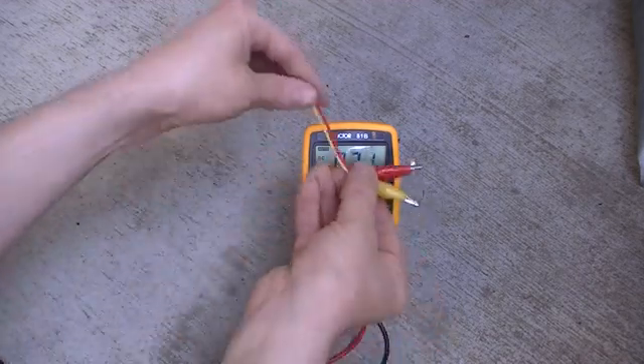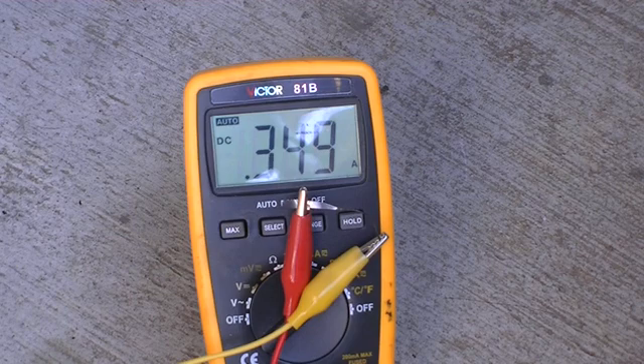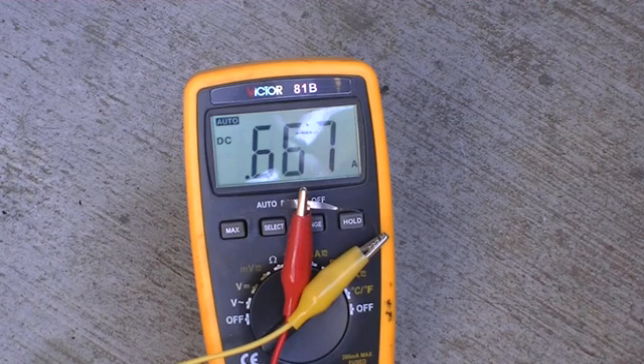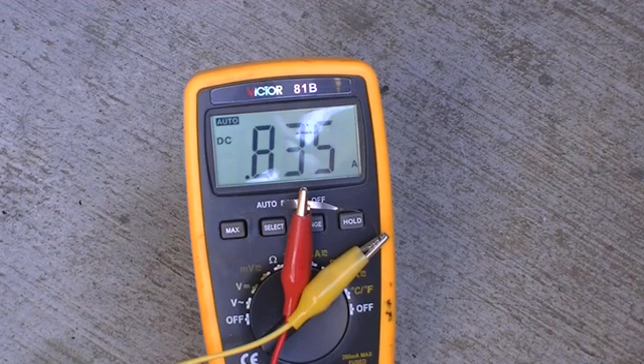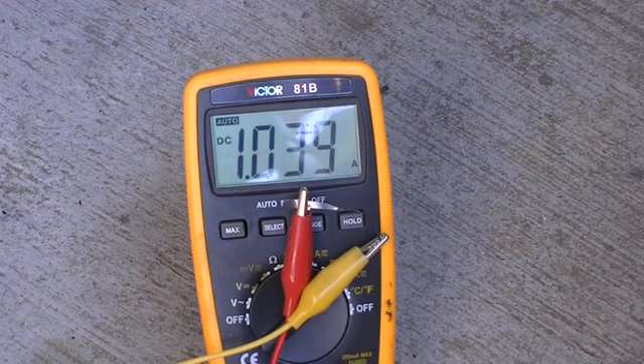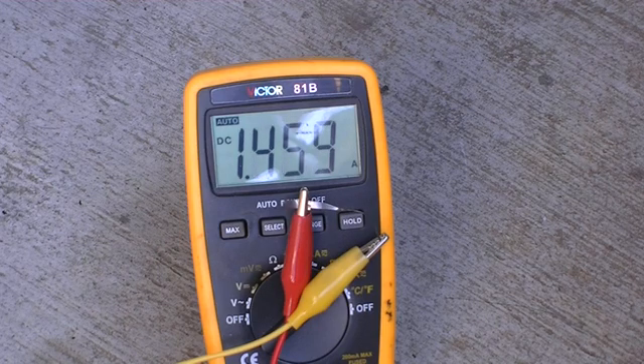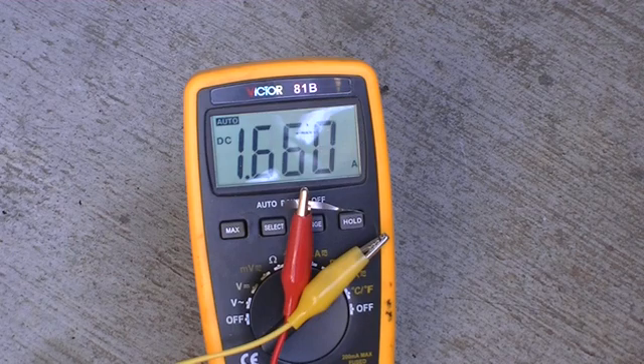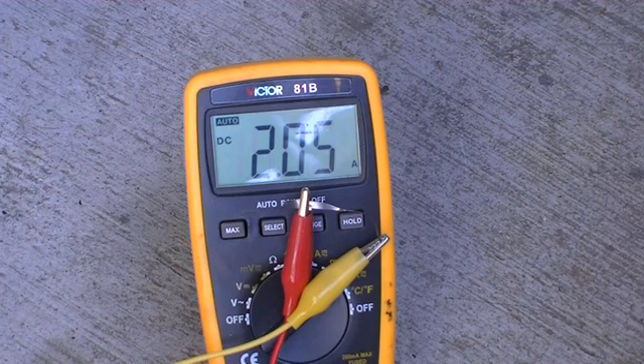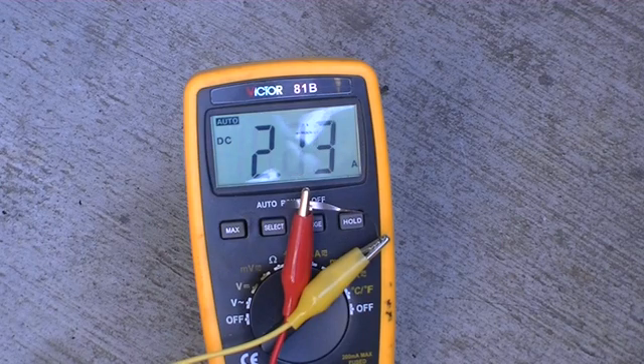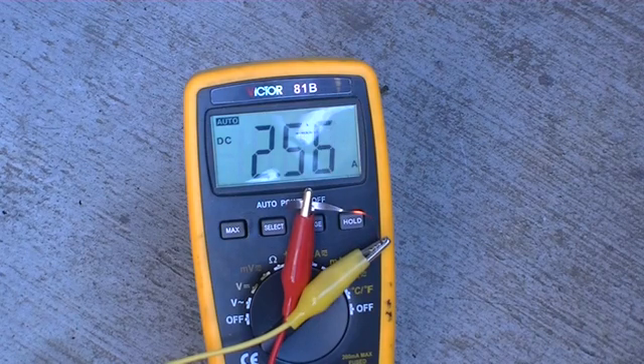The shape of a dog bone places the thin section in the middle, so this is going to have the area of high electrical resistance. This should heat up by the passage of current according to I2R and produce the ohmic heating. When we hook our tantalum metal up to our power supply and increase the current, you can see for a brief period there is a glow before the strip breaks. This is due to a high temperature reaction with oxygen and nitrogen in air.